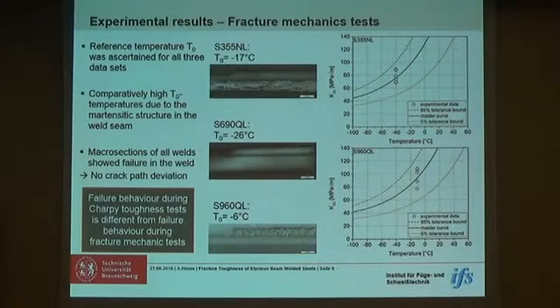A first conclusion can be drawn that the failure behavior during the Charpy toughness tests is different than the failure behavior during the fracture mechanic tests. So we cannot conclude one macroscopic failure pattern which occurs in the Charpy toughness tests and predict the macroscopic failure behavior for our fracture toughness tests or for welded components.